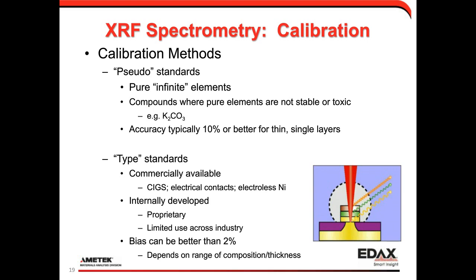So, maybe that nickel is 100 microns thick, and I measure that, and I tell the system, okay, this is a bulk material, 100% pure, and that'll give me a calibration coefficient for nickel. I can apply that calibration coefficient to all the elements, or I can make a calibration coefficient for each element in the recipe. It all depends on what kind of accuracy and what it is that we have available. And I'll show you an example later on where we calibrate for measuring thin layers just using a bare silicon wafer.